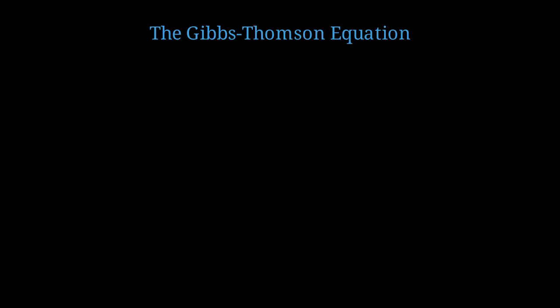The melting point depression is quantitatively described by the Gibbs-Thomson equation. This is one of the most important equations in nanothermodynamics. The melting temperature as a function of radius r equals the bulk melting temperature times 1 minus alpha divided by r. Here, Tm of r is the nanoparticle melting point, Tm bulk is the bulk melting point, r is the particle radius, and alpha is a material-dependent constant. The constant alpha equals 4 gamma SL times Vm divided by delta HF, where gamma SL is the solid-liquid interfacial energy, Vm is the molar volume, and delta HF is the latent heat of fusion. The key insight is that the melting point decreases inversely with radius. As particles get smaller, the melting point drops more dramatically.